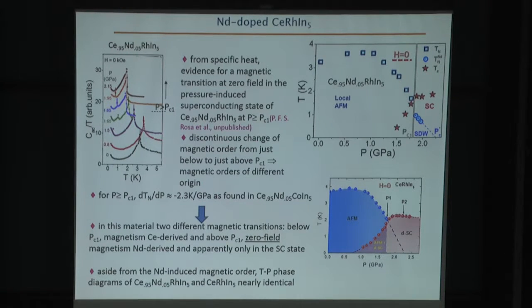So just comparing these phase diagrams for a sample with 5% neodymium substitution and pure cerium rhodium indium 5, we see that qualitatively they're very similar to each other, and that the most notable difference is the appearance of this phase boundary that so far we've only been able to detect inside the superconducting state of cerium rhodium indium 5.